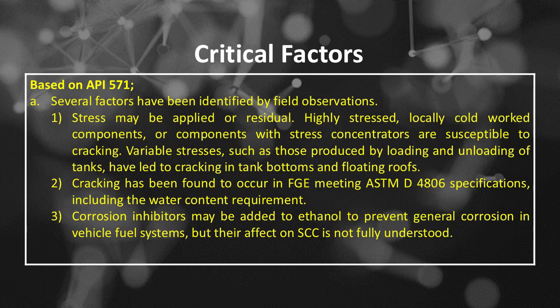Number 2, cracking has been found to occur in FGE meeting ASTM D4806 specifications, including the water content requirement. Number 3, corrosion inhibitors may be added to ethanol to prevent general corrosion in vehicle fuel systems, but their effect on SCC is not fully understood.